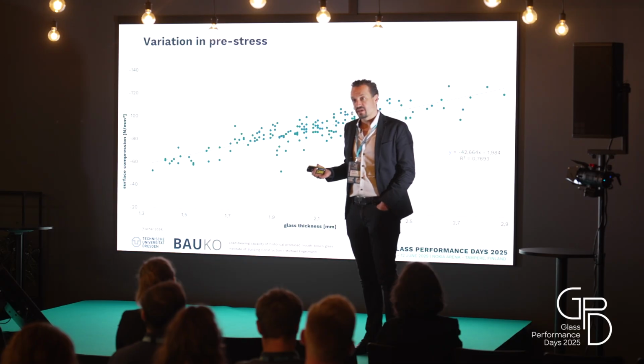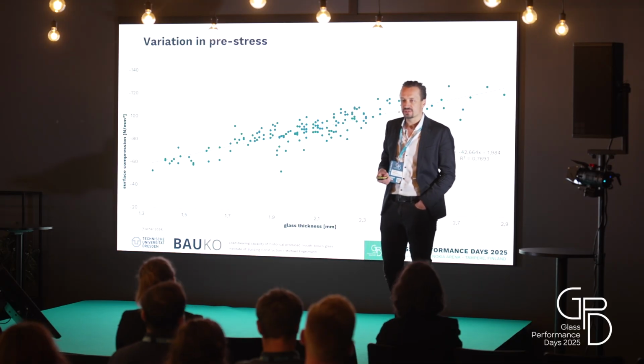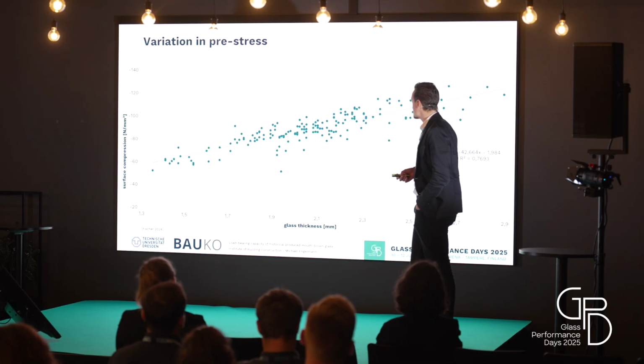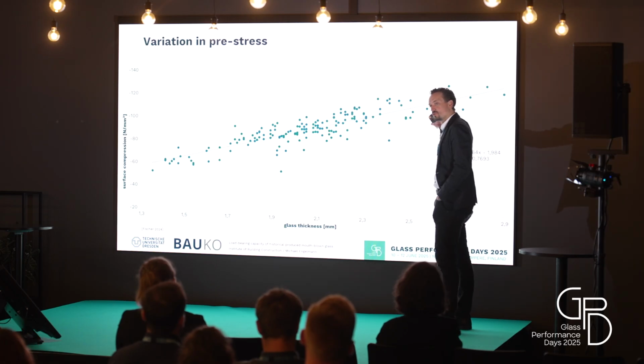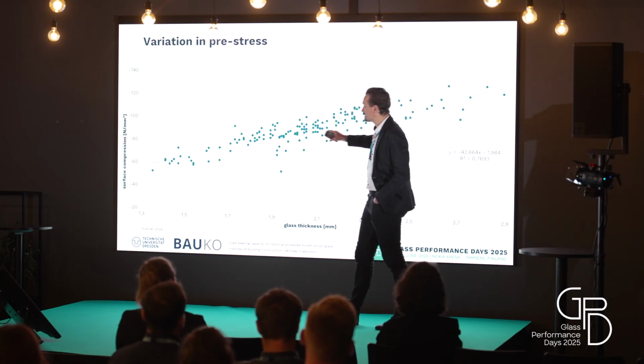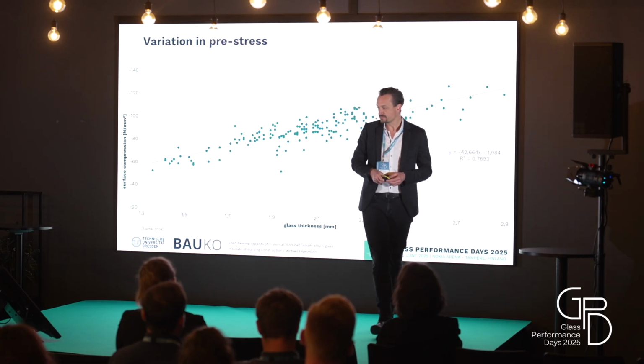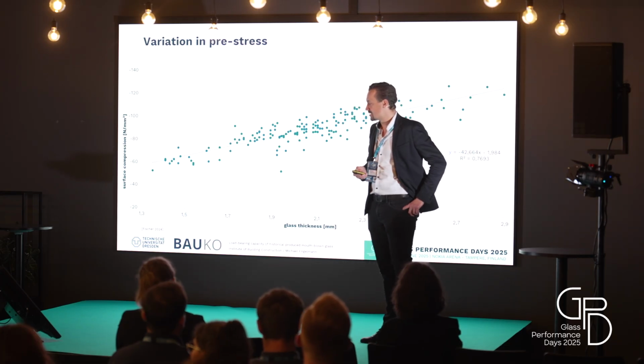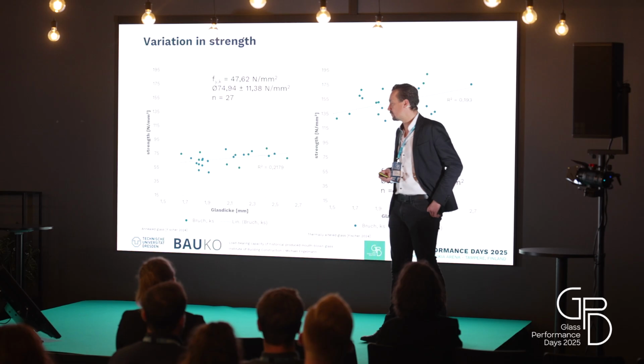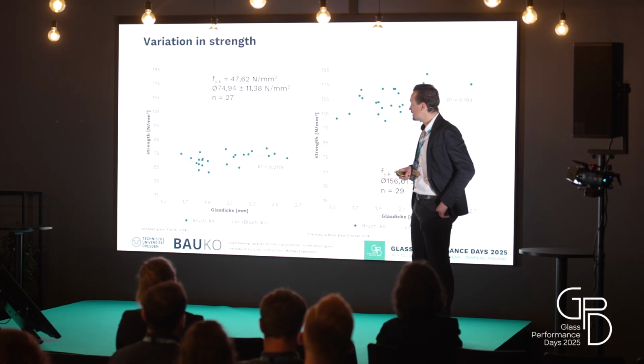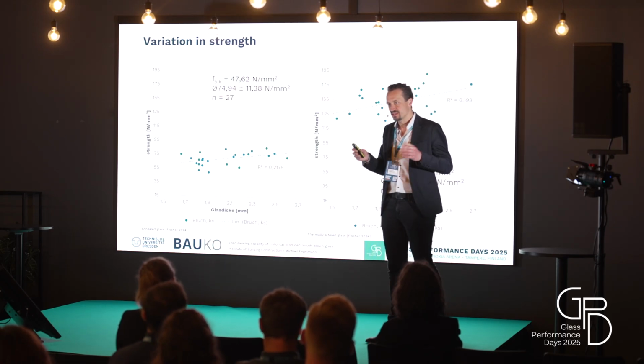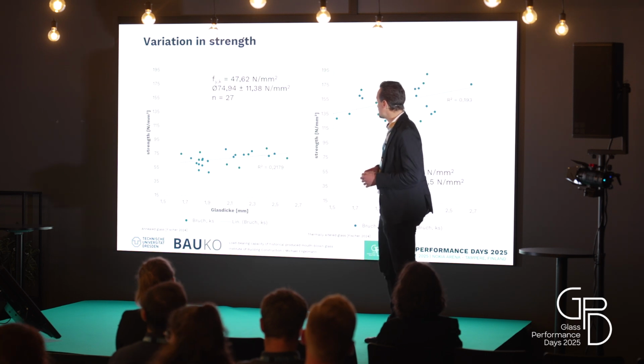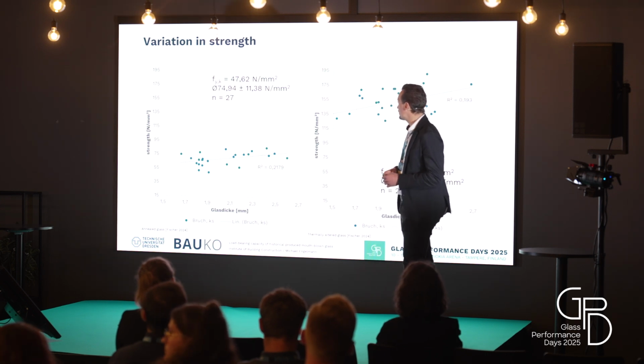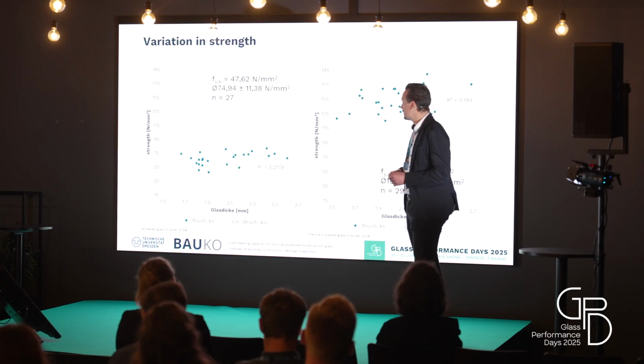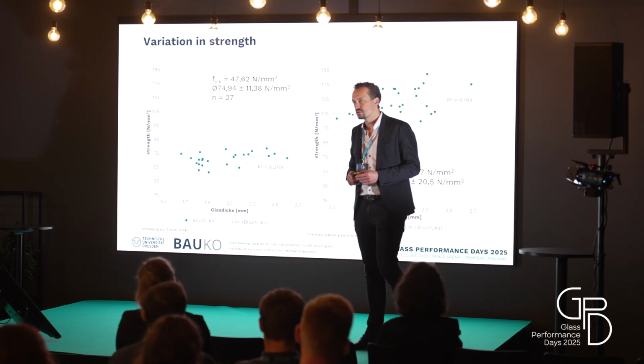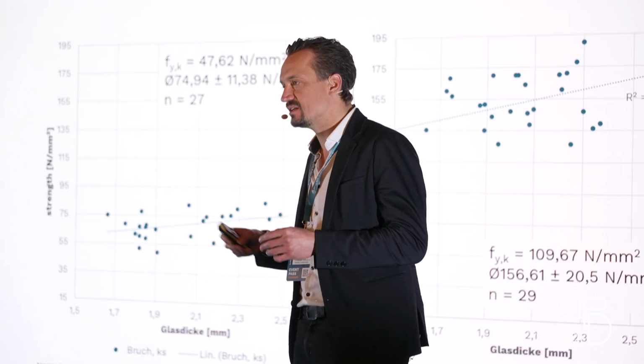The next question is then, can we actually reproduce this when we're looking into the strength of the samples? So when we are testing thick samples, will we find larger strength compared with samples that are a bit thinner? And here are the results for the strength in a 4-point bending configuration. On the left-hand side, these are the results for the strength of the annealed or non-tempered glass samples. So we have a characteristic value of about 48 megapascals, which I think is quite a good value, especially when you consider that this is annealed glass.